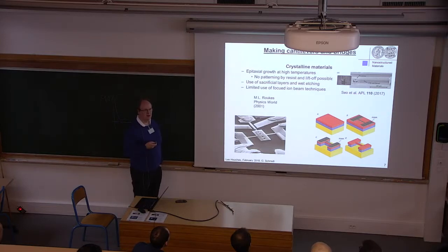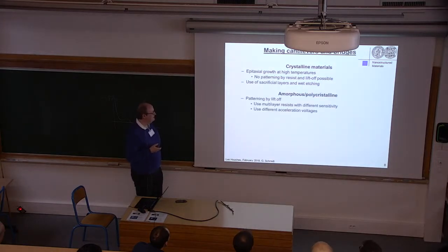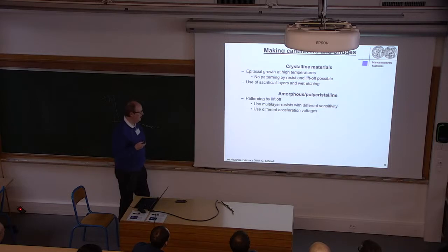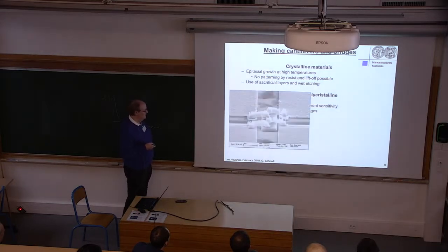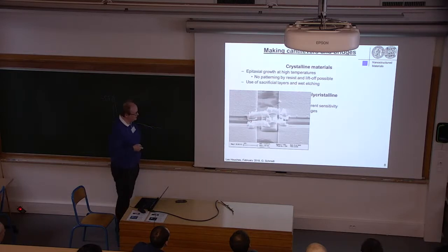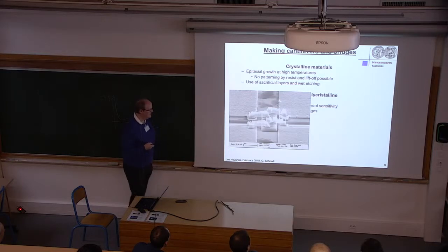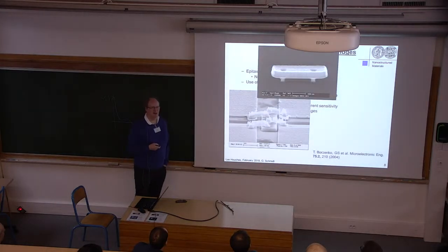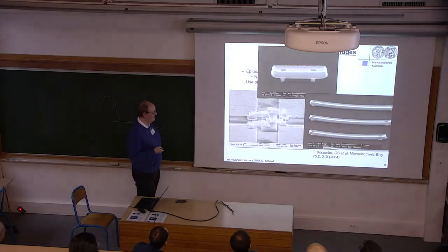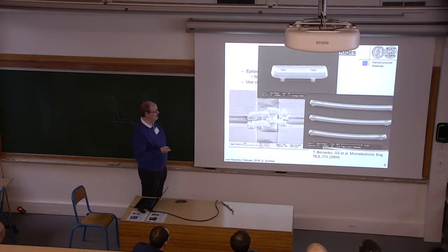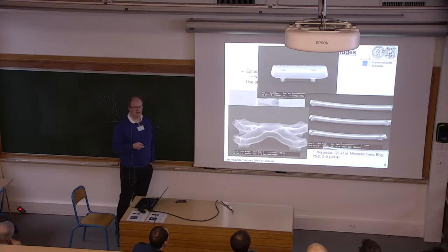There are also other processes, but they are based on lift-off, and then you need low temperature deposition. But it has been demonstrated first, I think, by Diana Mahalou from the Weizmann Institute. She developed a multi-layer process using resists with different sensitivity. And if you do this, then you can make these kinds of bridges. These were fabricated when I was in Würzburg. We had a lady there who adopted the process, and she was quite fast. It took her 48 hours to make these bridges after she got the recipe, but she said they don't look nice. So she developed another process which is based on different acceleration voltages, and this looks much nicer. But this is metal, that's the problem. But you can make very long bridges, so these were still limited in size. Here we can go to something like 10 micron, and we can also make complex stuff.